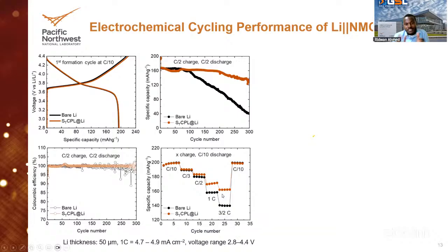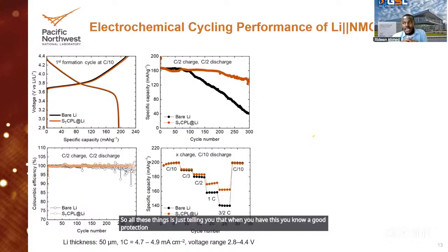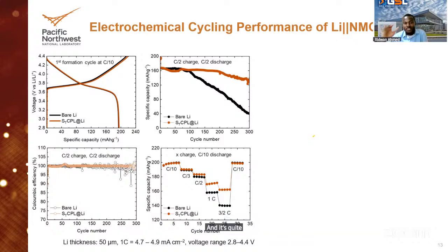So all these things are telling you that when you have a good protection layer on the lithium metal anodes, you can significantly improve the performance of the battery. And it's quite simple. Like I mentioned, it's just coating the material on top of the lithium. But you just need to make sure you find the right materials with the right combination of properties.